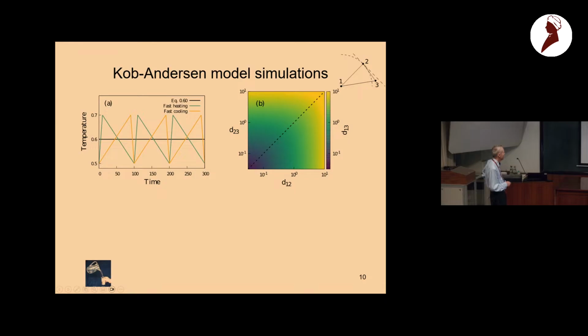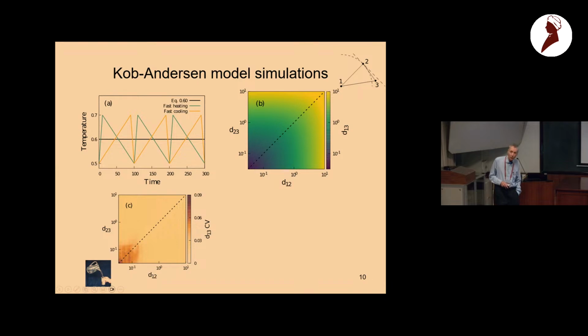This is done by Ian Douglas. So Kob-Andersen made a fast heating and fast cooling, and also another protocol. And then for all these many points generated, we plotted the distance between point 1 and 2 on the x-axis, and the distance between 2 and 3 on the y-axis, and then the color gives the distance between 1 and 3. But you cannot really see whether this one is uniquely determined, but you can see that on the next figure. This is the coefficient of variation. So for a given point here, this one should be a unique function of these two, and indeed the variations are very small. So we have confirmed this property that if you know two lengths of the triangle, you know the third one to a very good approximation.